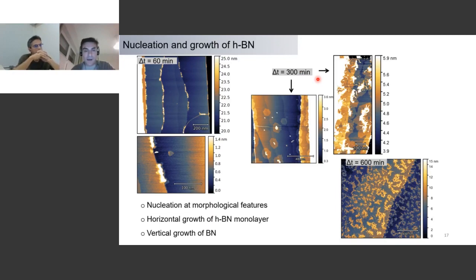On top of that, you have very high desorption of material, as I said before, because it's van der Waals epitaxy. You have a van der Waals surface, so most of the material, the boron and nitrogen that goes to the surface, it desorbs. But anyway, what you see here with time is that these islands laterally grow, and the height of these islands corresponds, as I said, to a monolayer of h-BN. And what is interesting is that you see that this nucleation, the seeding, is happening around defects, as I said, wrinkles or step edges.